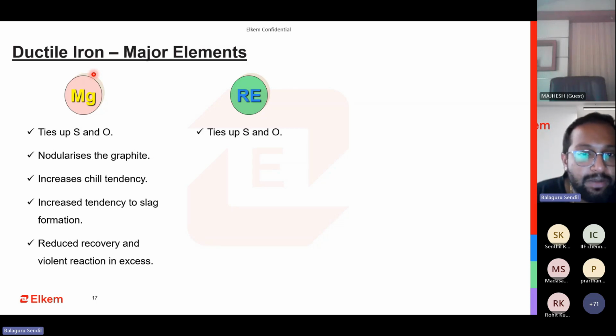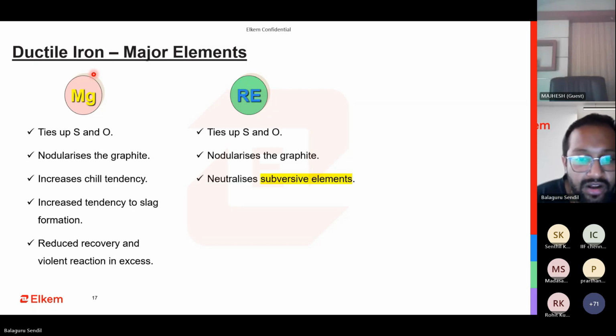That is why we have magnesium plus some amount of cerium and lanthanum, which will actually help you in the nodularizing process. It does the same as the magnesium. Additionally, it neutralizes your subversive elements. I am calling subversive elements trace elements. These can be something less than 0.001 or 0.01 in your cast iron. These can be manganese, chromium, titanium, boron, vanadium. All these are elements which are in the ppm levels. But these elements can directly impact both the size and shape of your graphite. So these are elements which are very dangerous.